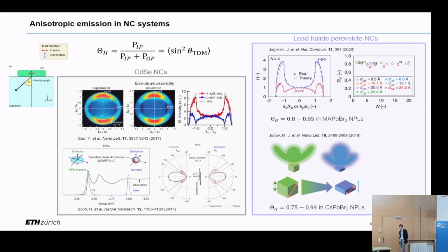This, together with some preliminary results, both in cadmium selenide nanocrystals, actually nanoplatelets, and lead halide perovskite nanocrystals, showed that these materials exhibit emission anisotropy, and so these are promising candidates.